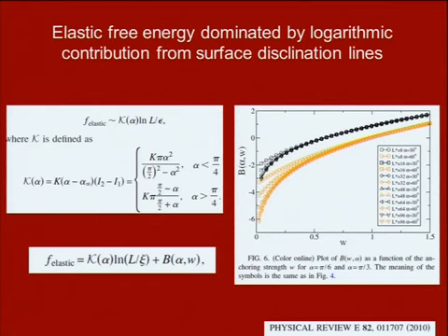Here we try to figure out how much of this elastic free energy comes from the surface, from the singularities in the surface, and how much does not. What we have here is some analytics. You can actually calculate the contribution from the surface singularities. José Manuel Romero Henrique did this, and this is all published. Then we can do the Landau-de Gennes. We can subtract this analytic contribution, and it should not depend on the size of the grooves.